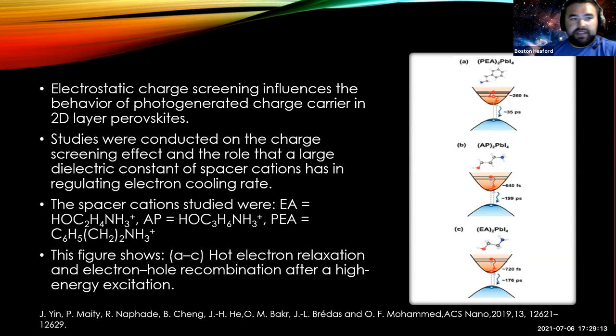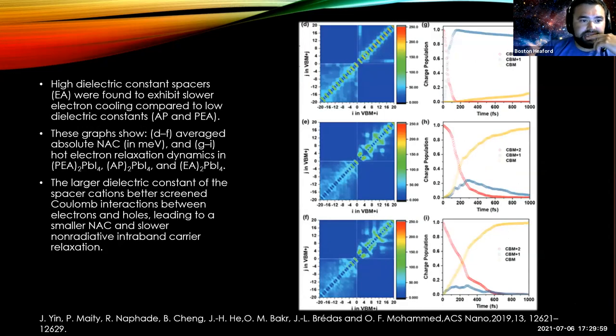So it was found that electrostatic charge screening influences the behavior of the photogenerated charge carriers in the 2D perovskites. And so studies were conducted on the charge screening effect and the role that a large dielectric constant has in regulating electron cooling rate. And so the spacer cations studied were listed there. And the figure shows the hot electron relaxation and electron hole recombination processes after a high energy excitation. And so high dielectric constant spacers were found to exhibit slower electron cooling compared to low dielectric constants.